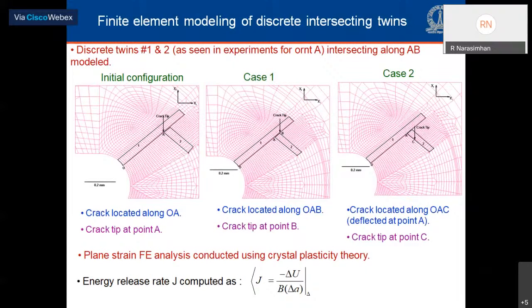One of the things that we wanted to understand, as I pointed out in the earlier slide, is the deflection of the cracks at the intersection between two twins. What is the origin for that? In order to investigate this, we took two discrete twins from the exact variants which we saw in our experiments corresponding to orientation A, and put them in our FEM model. So that's what you see here: two discrete twins, 1 and 2, which are intersecting along a line AB.